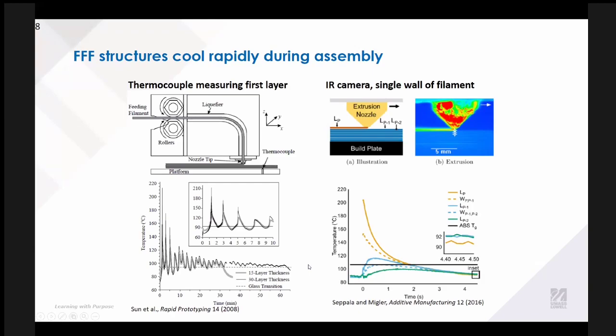Okay, so people have been interested in temperature profiles in FFF for a long time, and the reason for that is that the structures are extruded in a molten state, and then they have to weld to the previous layer in order to evolve mechanical strength. And if that doesn't happen, you can have delamination, or you can have weak parts. So this time temperature information is important because it dictates how much interlayer diffusion can occur, and therefore what the properties of your part are going to be. People have been looking at this for close to 15 years.